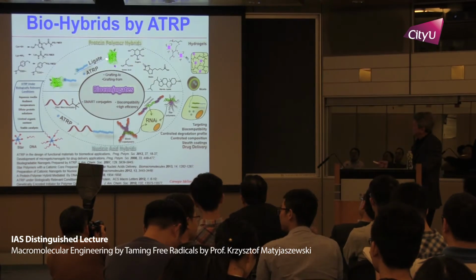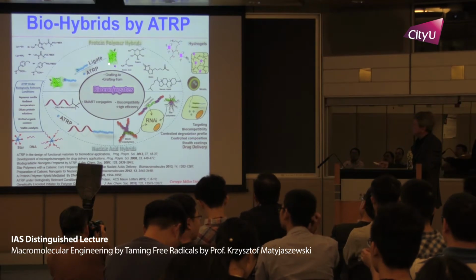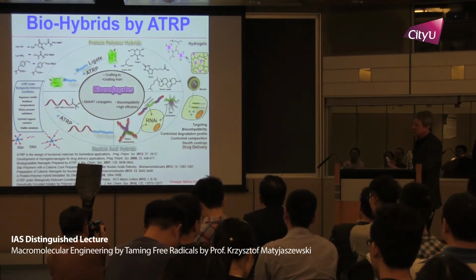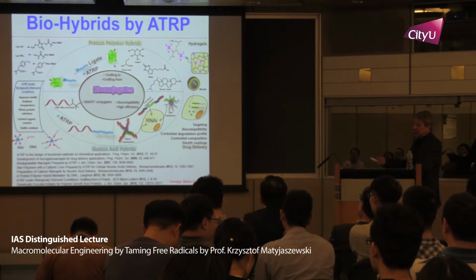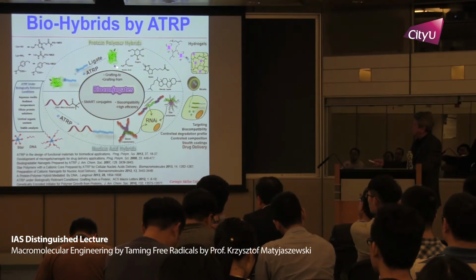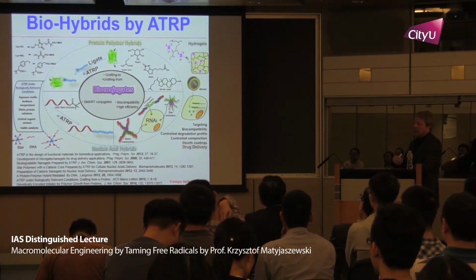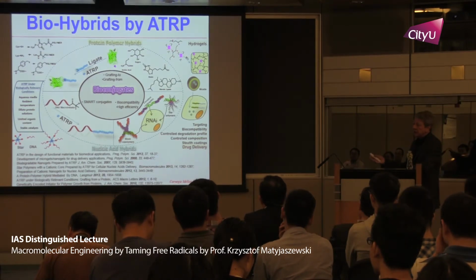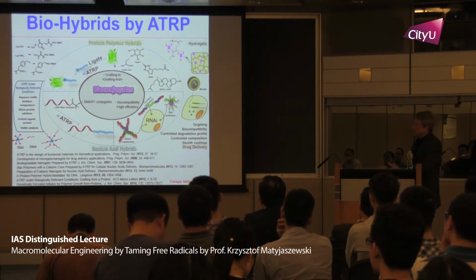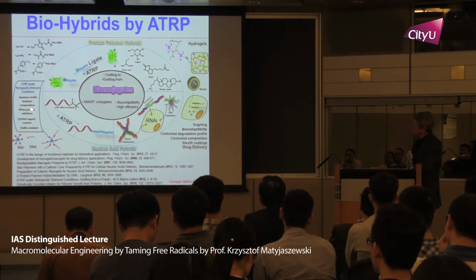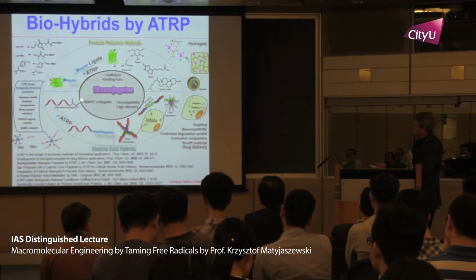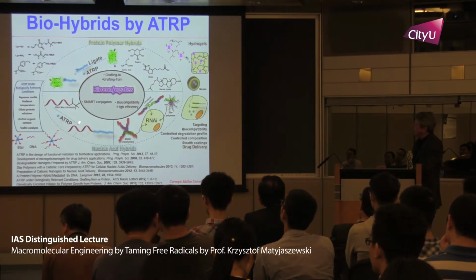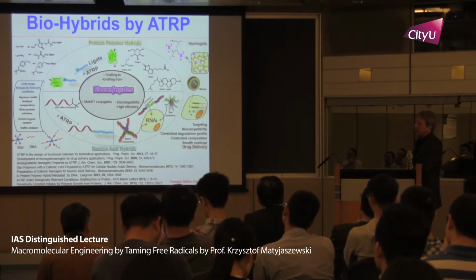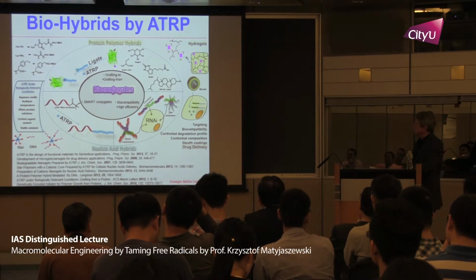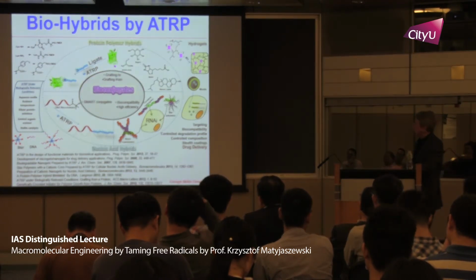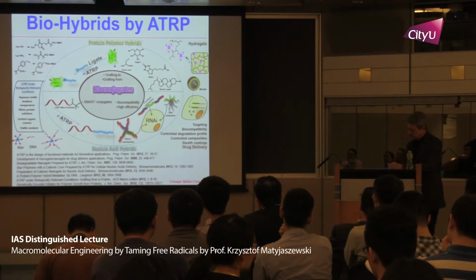Another approach is that you put functionality, for example, at a defined position on GFP protein. You add catalyst, you add monomer, and then you grow a polymer chain, and by dialysis, remove all of the unreacted monomer and catalyst. You can do the same, in fact, with DNA. We put DNA on a machine, we add a phosphoramidite with a bromoamide, and then we grow the corresponding polymer out of it. You can grow from 2 ends, you can grow also in the middle from different parts, making polyplexes and others.